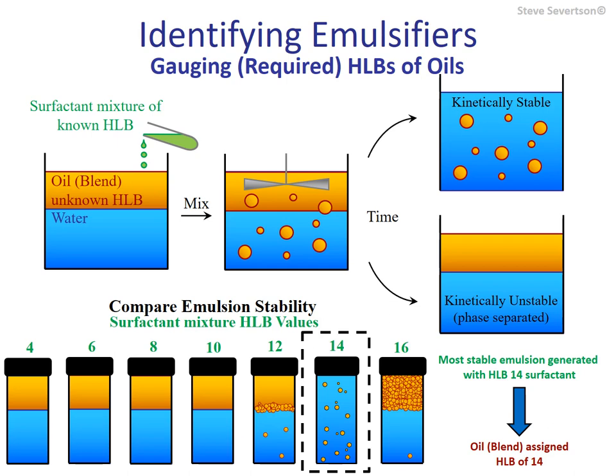The hydrophilic-lipophilic balance (HLB) of a surfactant can be used to determine the required HLB of an oil — the HLB of a surfactant or surfactant mixture that will generate a stable oil-in-water emulsion for a given oil sample. There is no universally accepted procedure for this testing other than generating emulsions from the oil with surfactants possessing a broad range of HLB values. Initial experiments typically use equal proportions of oil and water and a fixed surfactant concentration in the range of 10% to 20% based on oil weight. The method used to generate the test emulsions should be the same for all samples, and samples are often allowed to stand for 24 hours prior to stability assessment. Once the HLB of the oil is determined, various surfactant mixtures can be tested using the oil's required HLB value as a guide for the mass fractions of the emulsifier components.